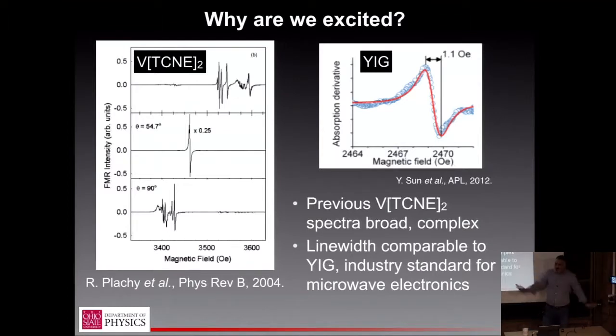But then we just mapped out all of the phase space that we could: the temperature of the V(CO)6 precursor, the temperature of the TCNE, the substrate temperature, the flow rates. We have a plot of the FMR spectrum for all these different parameters, and then you can make a phase diagram and say, okay, if you're operating in this regime of phase space, then you get really nice FMR lines. The tricky thing is that's maybe 30% of the phase space. For 80 to 90% of the phase space, you get great DC magnetic properties. So it's not that anybody missed anything big. It's just that the first time we saw the narrow line, we did get lucky. Then we said we want to be able to do that again, and we did this mapping, and we realized that parameters needed to be more tightly controlled than they had been in the past.